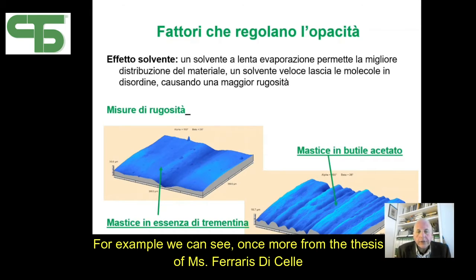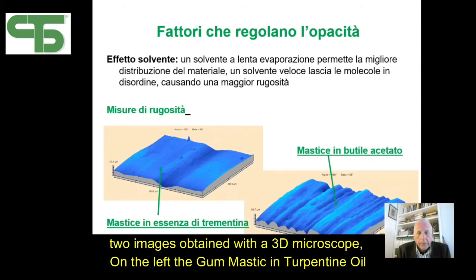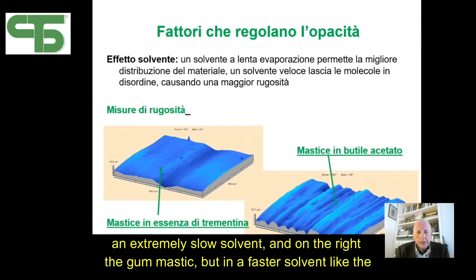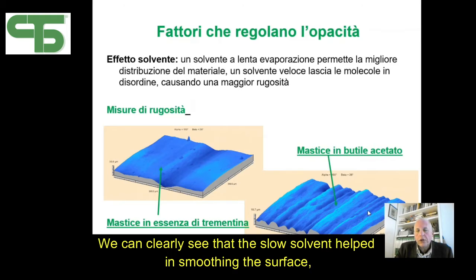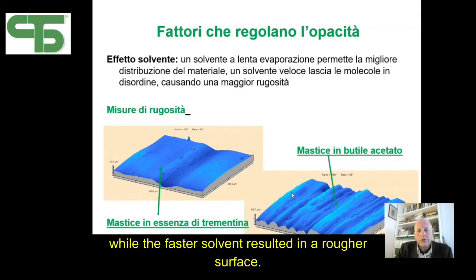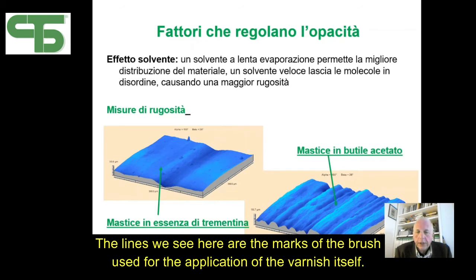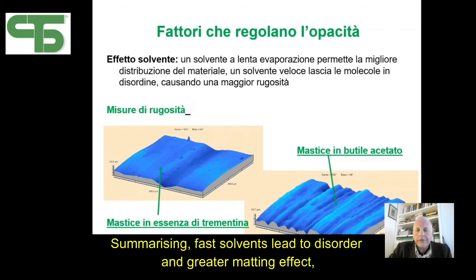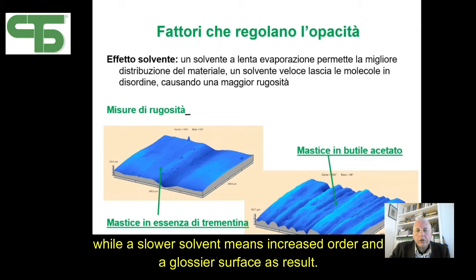For example, we can see once more from the thesis of Miss Ferraris di Celle two images obtained with a 3D microscope. On the left, the gum mastic in turpentine oil, that's an extremely slow solvent, and on the right, the gum mastic again, but in a faster solvent like the butyl acetate. We can clearly see that the slow solvent helped in smoothing the surface, while the faster solvent resulted in a rougher surface. The lines we see here are the marks of the brush used for the application of the varnish itself. Summarizing, fast solvents lead to disorder and greater matting effects, while a slower solvent means increased order and a glossier surface as a result.